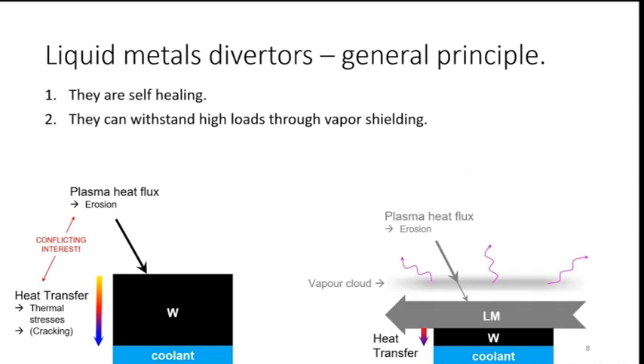For a liquid metal diverter, you can then immediately see why this might be a good idea. So the plasma heat flux again erodes some liquid metal, but that's fine because you can have a liquid metal flow and there can be replenishment. And so we have point 1, self-healing. And the evaporated metal goes into what we call a vapor cloud. But this vapor cloud also acts as a sort of shield, hence the term vapor shielding. So power is dissipated by this cloud because the cloud heats up, the particles are lost elsewhere, or maybe they radiate. And this, we think, or thought, and now we know for sure, can be a very effective way to dissipate heat.